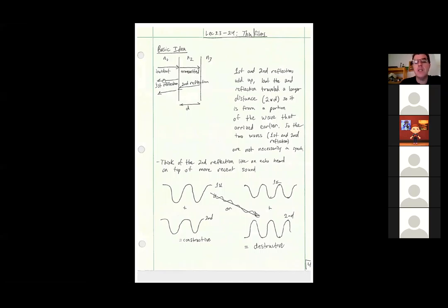But the vast majority of the physics that you need in order to at least make a qualitative prediction just comes from considering this first reflection and this second reflection. And you can get tremendously accurate predictions just from considering those two reflections. In fact, we can even show, as we will later, for an anti-reflection coating, that if you were to make a really simplified calculation and approximate this transmission coefficient as one, even though it can't be exactly one, and then approximate this transmission coefficient as one, you would get the same answer that you would get if you took into account the fact that this transmission coefficient is not quite one, and this reflection and then there are other reflections here. If you took all of those effects into account, you'd get the exact same answer.